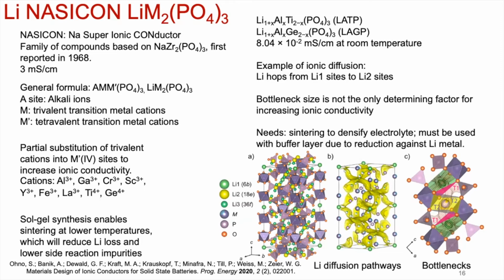But when you go into the lab, what you find is if you have an oxide, you're going to have to sinter it, right? You're going to have electrode-electrolyte contact issues. So starting out, the crystal structure is ideal, but once you make that actual compound, you're working with the powder, and that's when all the engineering challenges come up. That's when you call your mechanical engineering friend and say, let's work together, because it's the bigger challenge. Yes, Alex.